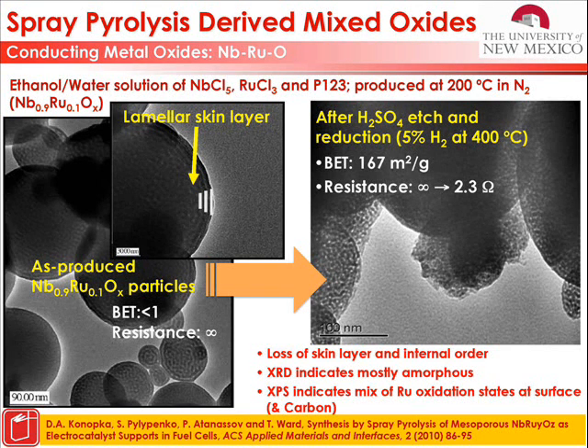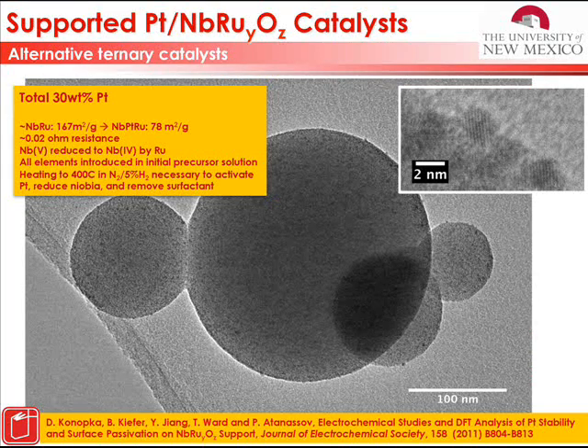So it deposits itself on the surface of the carbon, at the same time eats away the amorphous carbon. As you see, only turbostratic structure of the graphitic carbon is left, and then that carbon is packed together into these 3-dimensional ball-like structures, and those actually, if you can process them to include the Nafion inside and the Teflon inside in desirable reactive mix, with that, you obtain spheroidal particles that are micron size, several microns in size.